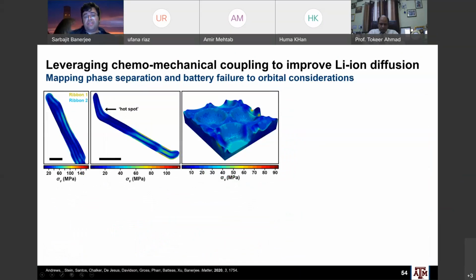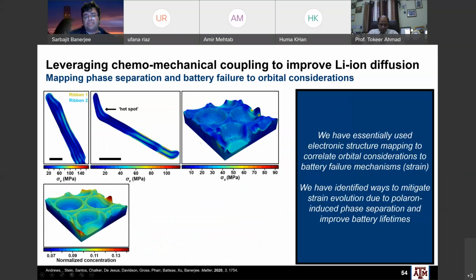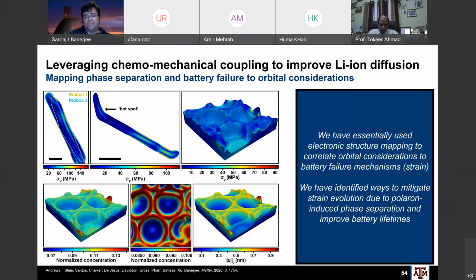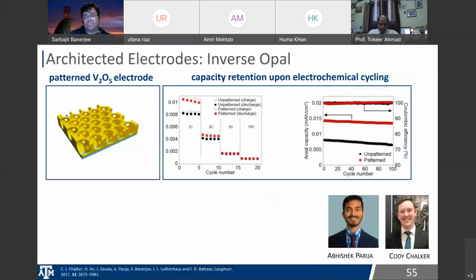So if you now take a look at the stress map, you can see here in a bent wire or single wires have these large hot spots. That's no longer true for these 3D curvatures. Another way of thinking about it is that the 3D inverse opal templates can breathe in and out of the plane. They can expand in and out of the plane, right? And by expanding in and out of the plane, they can mitigate these polaron-induced phase separations. And therefore, this is a great way to get very fast charge-discharge rates without destroying the battery, without building up these large stresses in the battery.